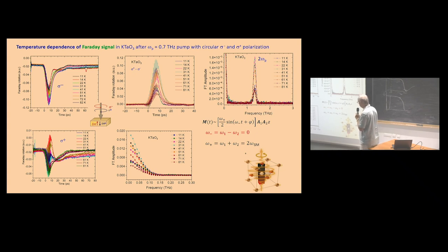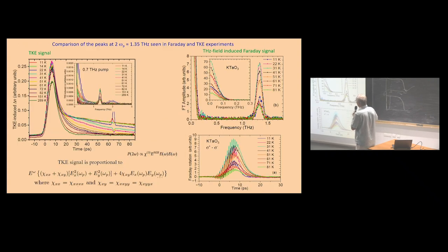But when we are out of resonance, we still see some intensity. So I think this is not the magnetic response, but this difference is the magnetic response. And we measure as well the electro-optic Kerr effect. It means this birefringence, which should be quadratically dependent on electric field. And again, we see the pumping peak here, and here an increase, which reminds me of the one here as well, but it is much weaker. So this electro-optic Kerr effect is much weaker, and this difference is due to the magneto-optic effect.